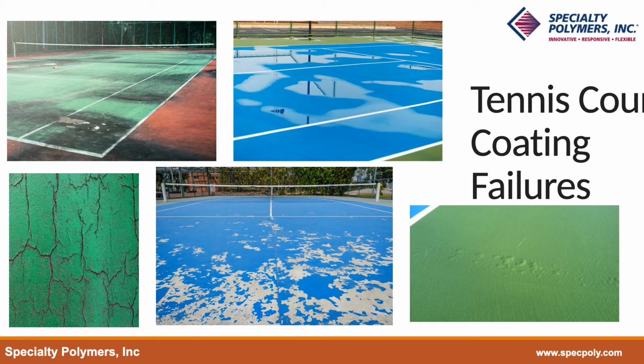But in older courts, you sometimes see cracking. Usually this is from cracks in the asphalt substrate, which gets more brittle as it ages. The cracking can have many causes, but it can sometimes be accelerated by stresses from temperature differences between the white lines and the court. I mentioned that you can also get loss of sand from abrasion on the court.